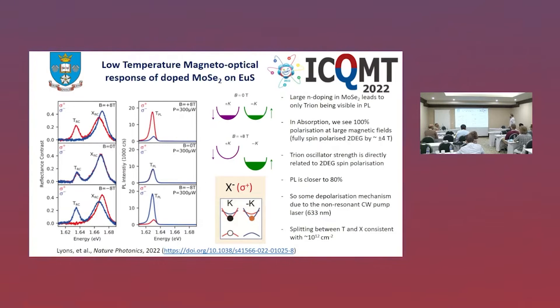When we cool down our sample and introduce magnetic fields, thanks to the large n-doping, we actually only see the trion resonance in our PL emission, due to the high Fermi energy. However, in absorption, you can see both resonances — trion and exciton.